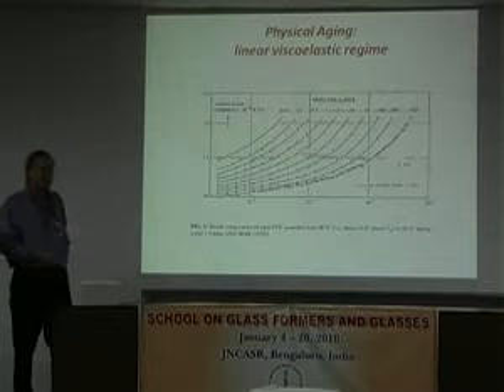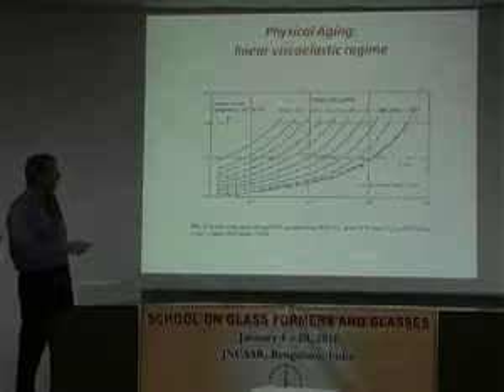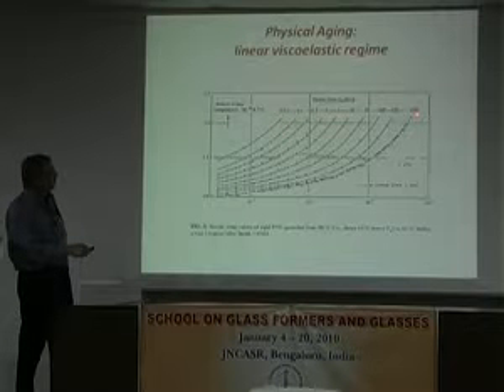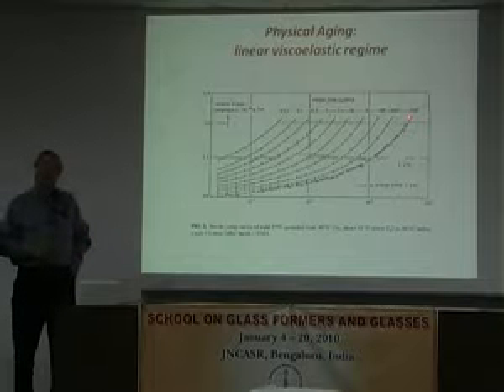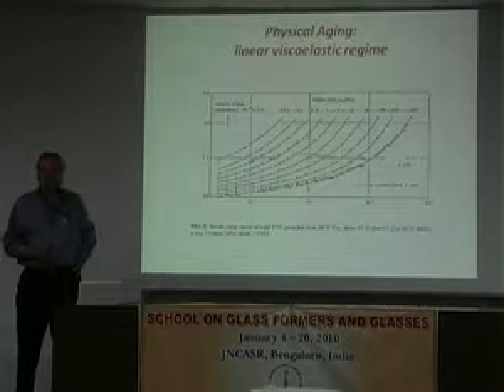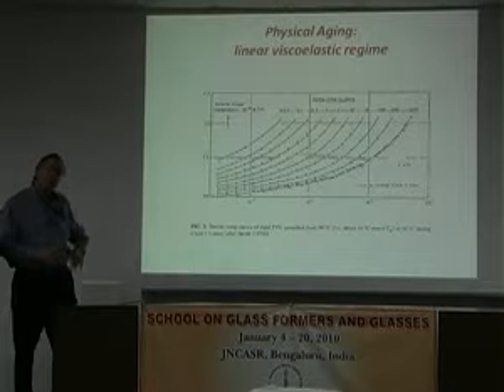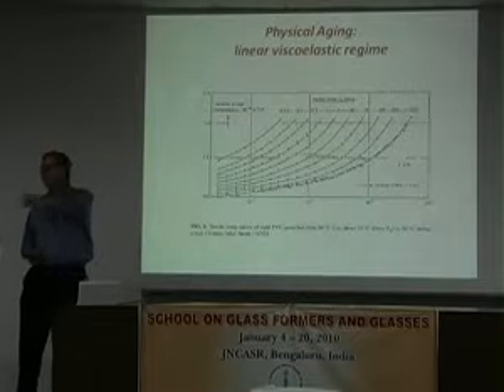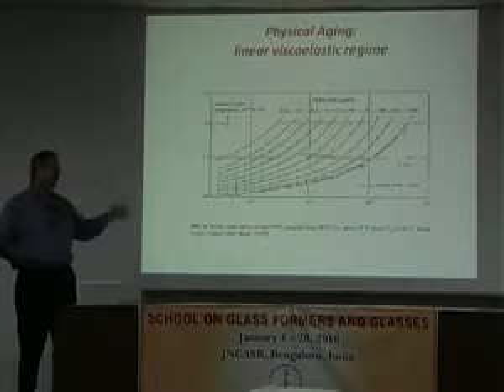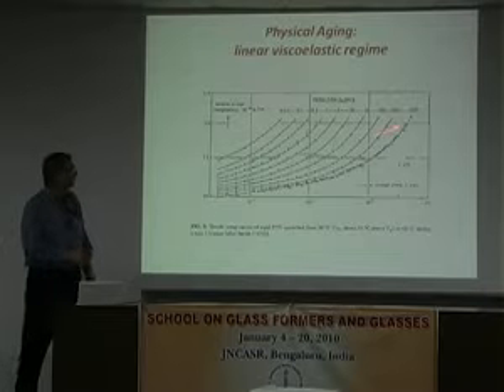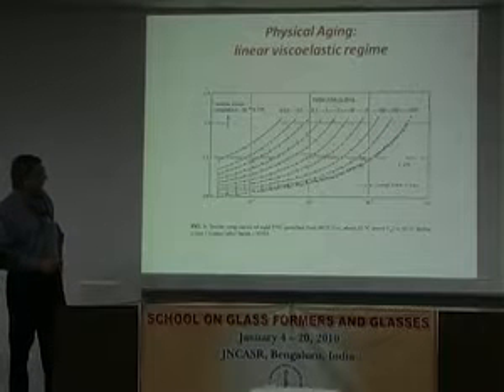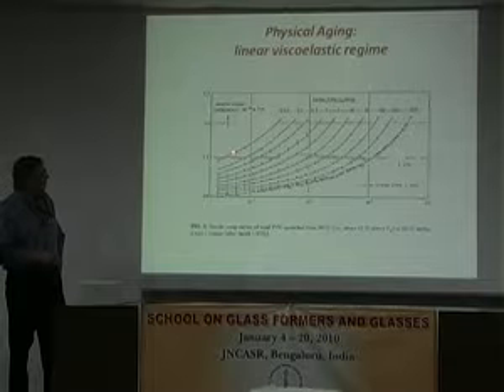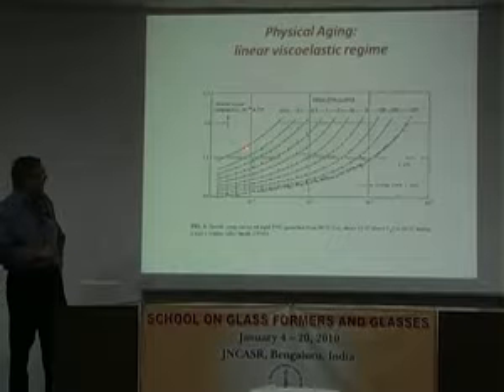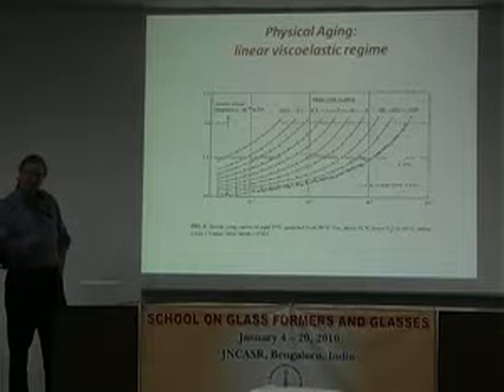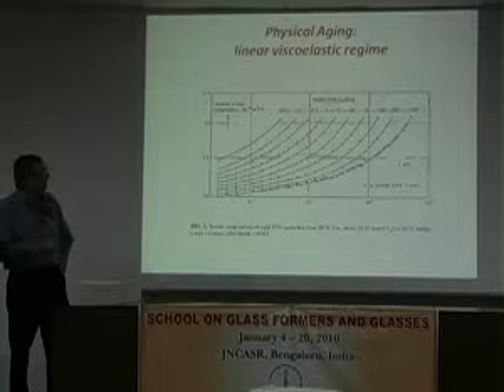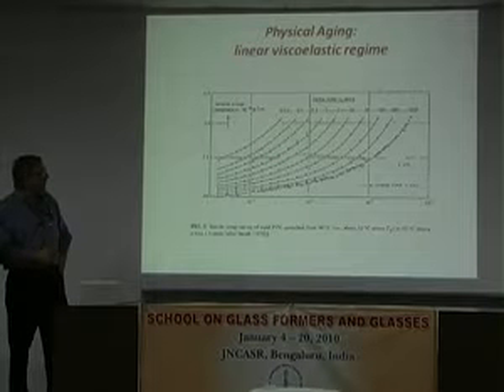Sometimes you need those, sometimes you don't. But he needed small vertical shifts. And you can see how long this is going on. This is a 1,000-day experiment. Okay? So very long experiments. And we know now that, if you're at low enough temperatures, it goes on for more than 1,000 days, right? But that's a 3-year or so experiment almost. So now with this time shifting, you can define a shift factor, a sub te, because he called it elapsed time, and then you'll find how that behaves.